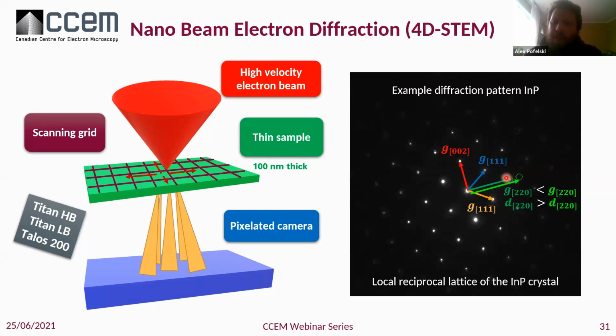And if there is some deformation, this dot will move. So in this case here, I just put it a little bit further. So let's imagine this case when you have the G that is bigger than the previous one. This will mean that the d-spacing is actually shorter, because there is an inverse relation between the G, the distance in reciprocal space, and the distance in real space. So by looking at the variation of the position of the diffraction spots, you can find the deformation, because this is a direct representation of your crystal lattice.